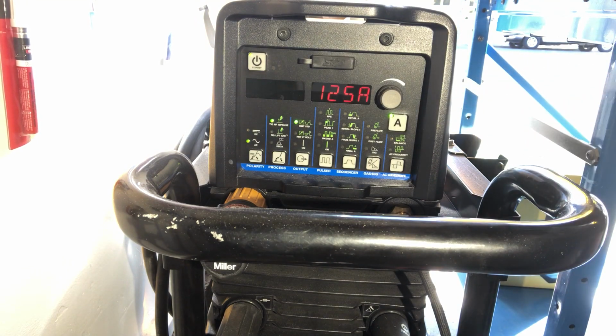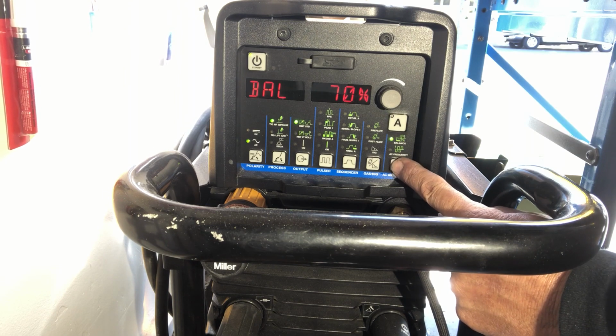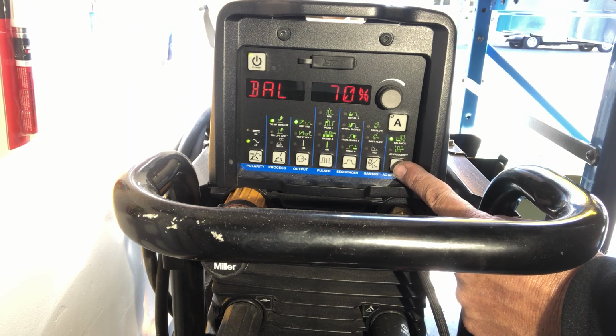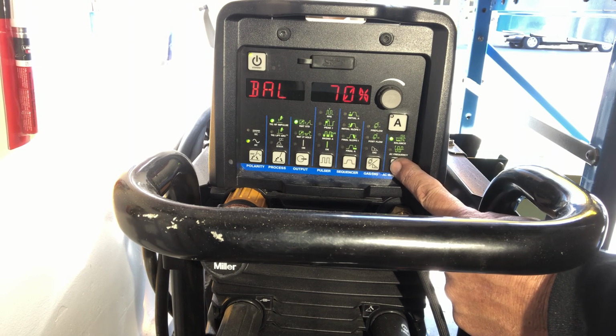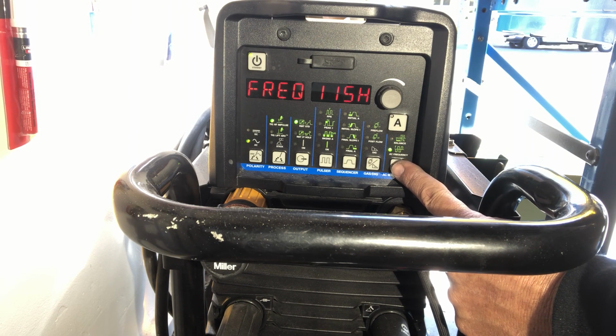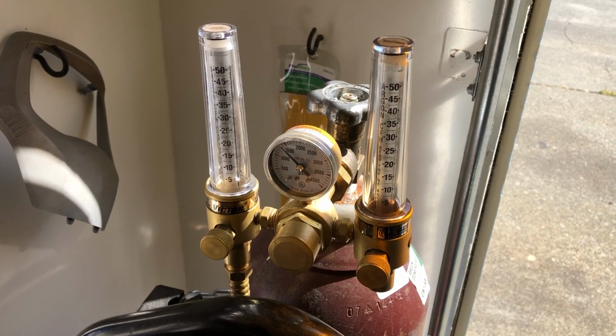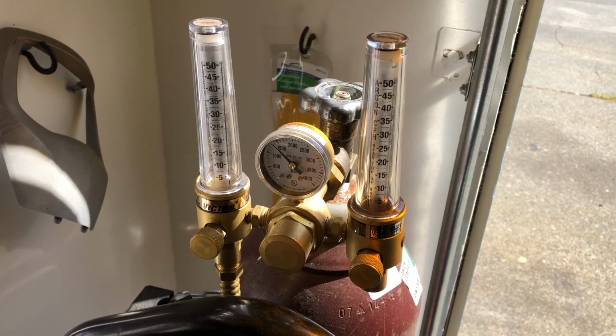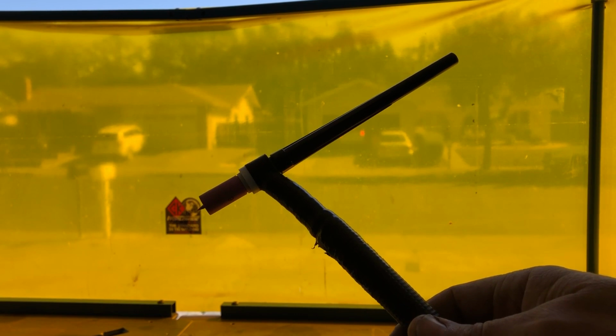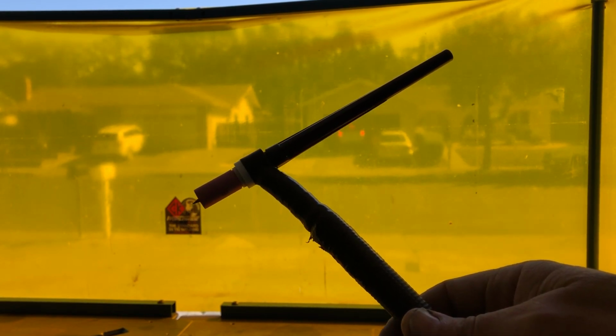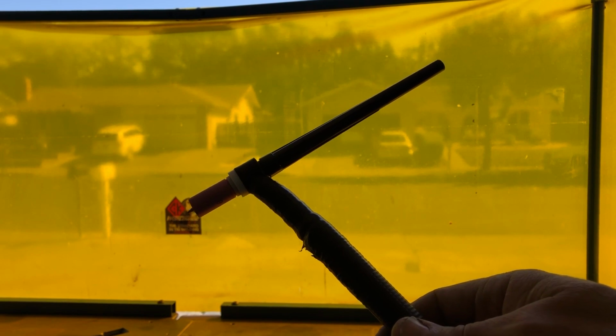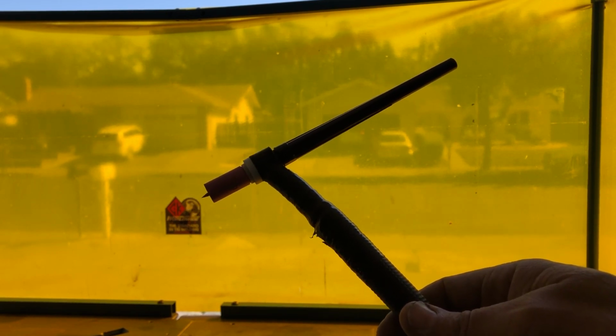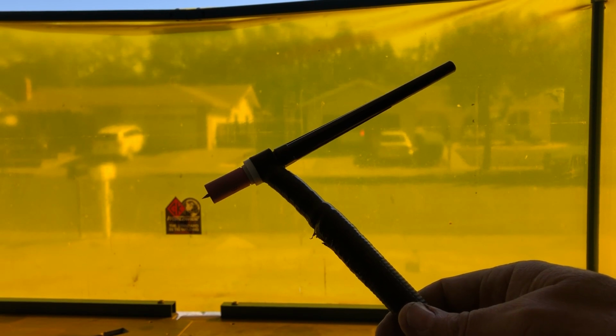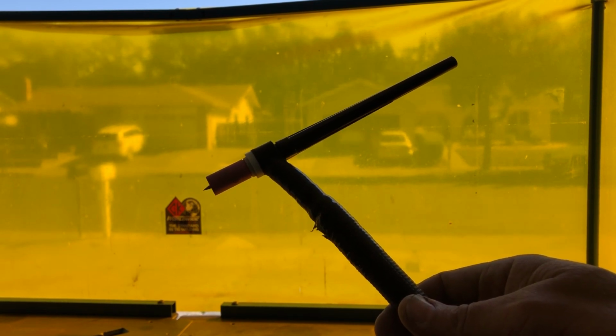My current is 125 amps because this is .120 wall material. My AC balance, I'm going to start with 70% balance. I might adjust that later. I'm using 115 hertz for the frequency because I couldn't decide between 110 and 120. I'm using pure argon, and I have it set to 15 CFH. I'm using 3/32 inch 2% lanthanated tungsten, sharpened to a 30-degree angle, and I did not blunt the tip. I'm using a number 6 standard cup, and of course a 3/32 standard collet.